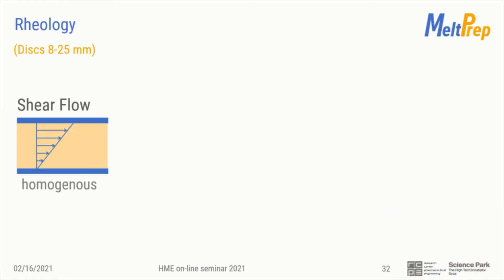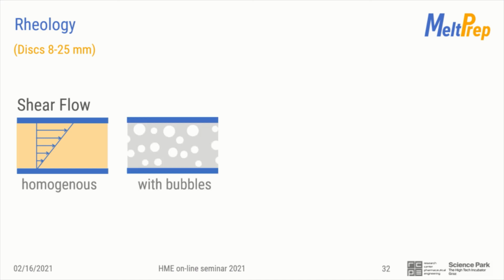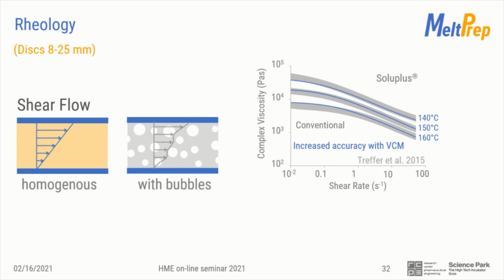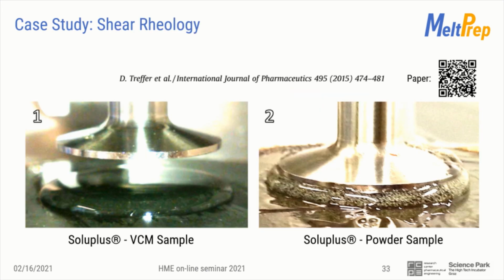Rheology on VCM samples can help to find the processing window of your extruder. During my PhD, I realized quickly it can only help if you receive reproducible data. During viscosity measurement, shear is applied to a molten sample and the required force is recorded. A rheometer assumes a homogeneous sample. Inhomogeneities, like bubbles, lead to falsified data. Compare these two images, taken just before the measurement. The perfect sample on the left, and on the right a sample with many bubbles, without proper sample preparation.